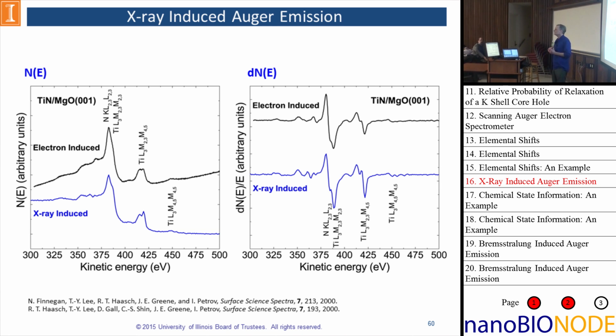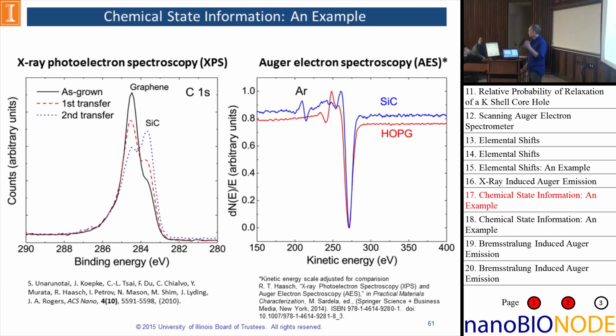Because of the design of our photoelectron spectrometer, you'll notice that we get a little bit better energy resolution with the X-ray induced Auger spectrum as compared to the Auger electron induced spectrum. That's because in order to make the Auger spectrometer of a coaxial design like we have, they have to make some sacrifices in terms of the energy resolution of the instrument. And in most cases, we use Auger for elemental analysis, but in many cases, we can get chemical selectivity.